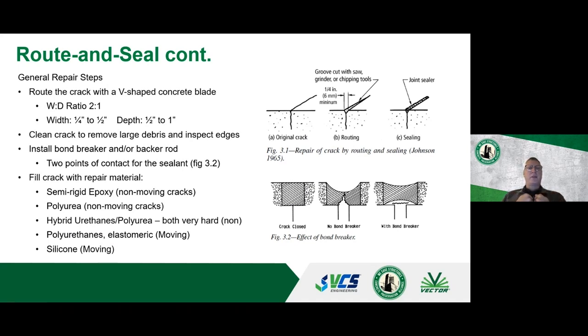Now, if you add a third element and you bond that repair material to the bottom of the crack, let's say your crack's not that deep, but you bond it to the slab underneath, you've now created a third point by which it's bonded. If it tries to expand or contract, it's going to tear because it's bonded to that bottom part. So there is a part in this repair procedure that you never skip, and that's putting a bond breaker in or a backer rod or something that prevents that from bonding to the bottom. There's a whole bunch of different materials. I have those listed here.